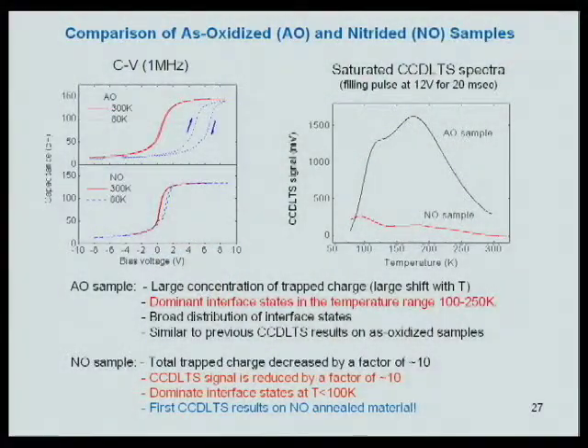The standard capacitance measurements are how we determine the energy distribution of the defects that I showed you before. But in addition to that, in our lab we can measure the rate at which charge is trapped in those energy states and the rate at which it's emitted. This enables us to distinguish different trap species. Here I'm showing you a little data. These are standard CV measurements taken at room temperature and low temperature. Right away you see that there's a huge shift that's much reduced in the nitrided samples. And this is just raw data, a saturated constant capacitance DLTS spectrum for the oxidized sample and then for samples that have been nitrided. We see that, yes, our technique also detects the fact that there are fewer traps or defects at that interface.